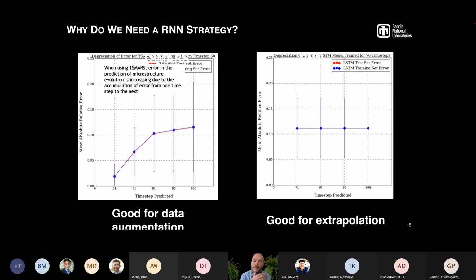One other thing that we tried initially was to ask, well, do you really need an RNN strategy to achieve this type of results? If you look at the classical time series extrapolation technique in applied math, people have been using the so-called TSMARS, time series multivariate adaptive regression splines. If you were to use that type of technique on your latent representation, what you see is that you would accumulate errors over time, which is not something that you want. So that's not very good for extrapolation of your data. However, if you use a GRU or an RNN or an LSTM type of architecture, the results on the right show that you actually get very good extrapolation on your results.